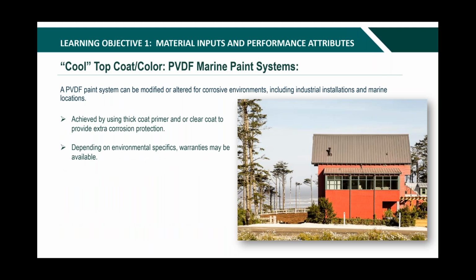So people do also offer a PVDF marine paint system, and it basically gets modified or altered in a corrosive environment situation, including industrial installations and marine locations. This is achieved by using a thick coat primer and or a clear coat to provide extra corrosion protection. And then depending on environmental specifics, warranties may be available for this paint system. So the marine paint, again, it's a little bit beefier, and how they achieve that is they thicken the primer coat and they add a clear coat to the top of the system.